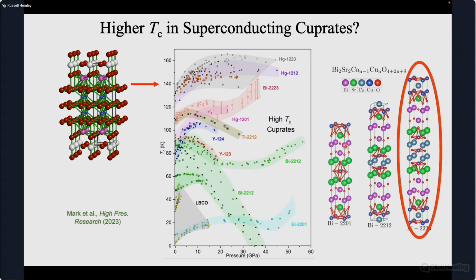And on the question of unconventional superconductors, I just want to have a very brief mention of superconducting cuprates. Do we see some of these same phenomena under pressure now as we approach megabar pressures in cuprates? This is a compilation of TCs for various cuprates up to, say, 50 GPa, work done by another student. We have the mercury compound here, which has the highest TC of the cuprates, but we have these other cuprates. In fact, the BSCCO cuprates here, the structures are shown on the right, are very sensitive to hydrostatic stress, but if you pressurize them carefully enough, you see this anomalous decrease and then a continued increase with pressure.